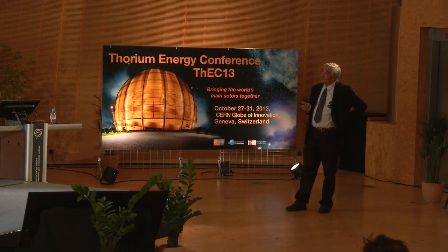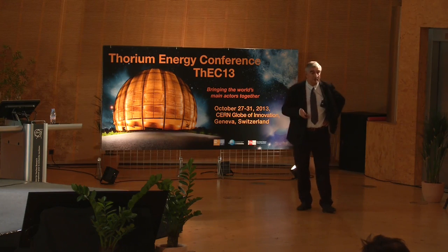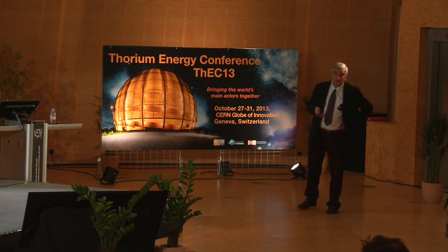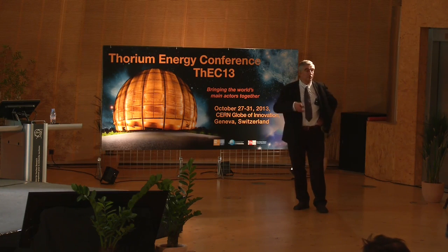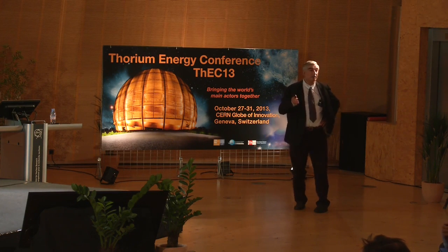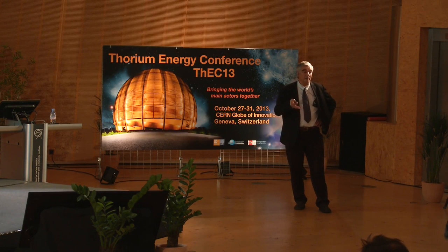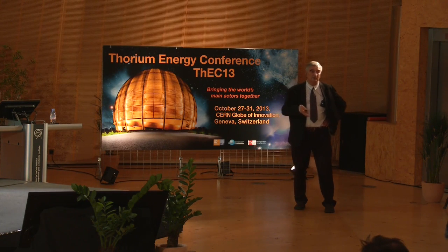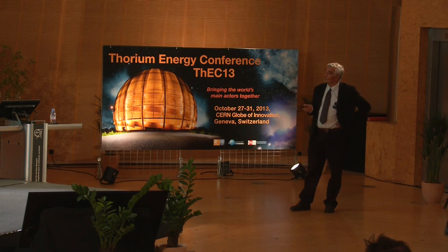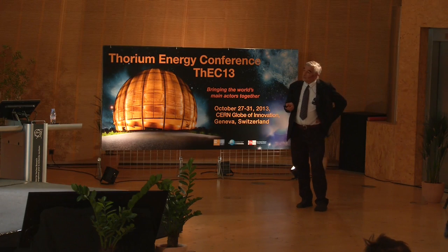corrosion, mechanical lead bismuth freezing and consequences of this expansion, for example, thermal expansion during the freezing of the LBE after the operation, in order to prevent any embrittlement of the target and any damage that could perturb the results of the PIE and so on. The lead bismuth water interaction also, and so on. So we had a lot of experiments to perform.